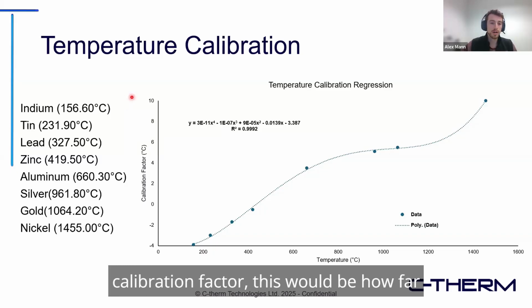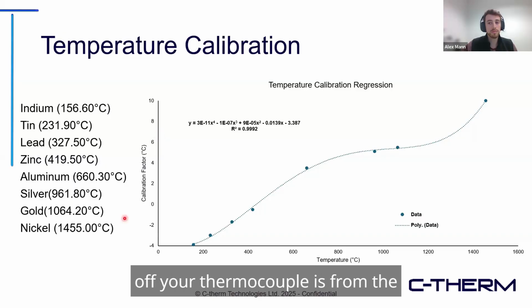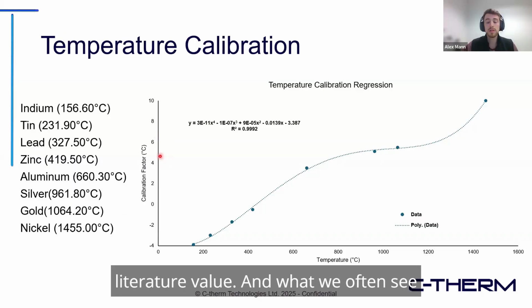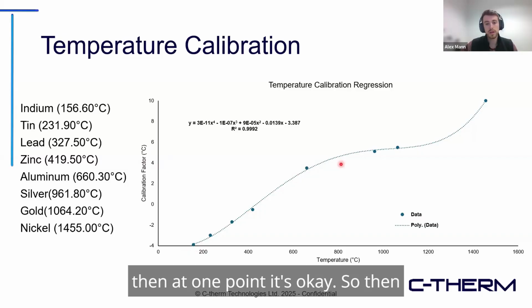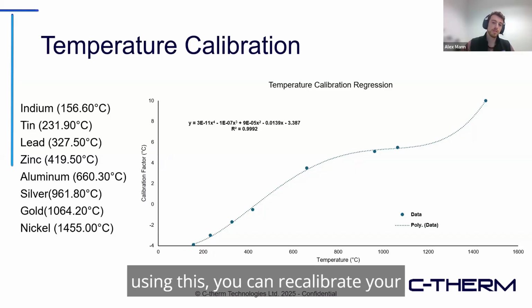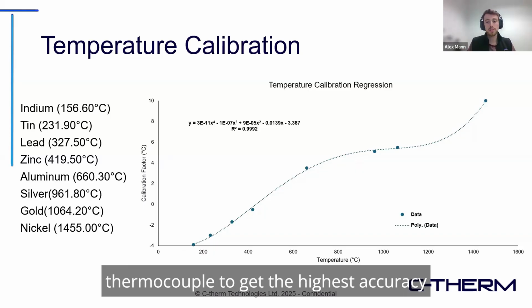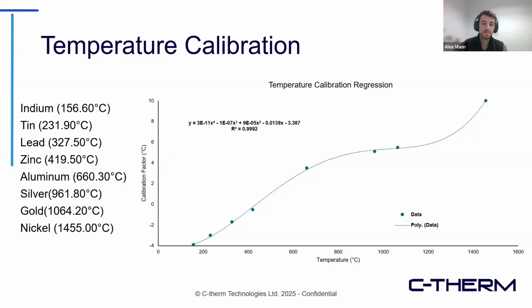So essentially here, our calibration factor would be how far off your thermocouple is from the literature value. And what we often see is an upward slope like this, and then at one point it's okay. So then using this, you can recalibrate your thermocouple to get the highest accuracy results.